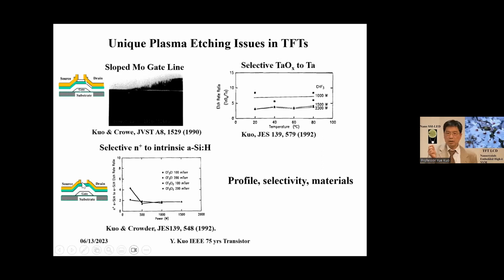Also, for example, in one bilayer structure, the N+ doped layer has to be etched selectively from the intrinsic silicon layer. So we need high selectivity. And this is the first report of obtaining selectivity of more than 1 for N+ to amorphous silicon. That enables the mass production of the bilayer structure of TFT.